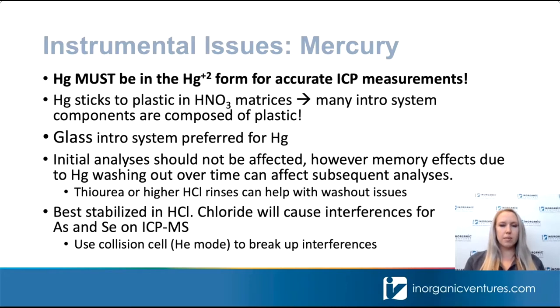The main thing to keep in mind when performing a mercury analysis on ICP is that mercury must be in the +2 ion form to achieve accurate results on ICP. Another thing to keep in mind is that mercury, when contained in nitric acid alone as the matrix, is going to stick to any plastic component, so it's going to absorb to those plastic surfaces, and many intro systems are composed of plastic. We do recommend using a glass intro system if possible for your mercury analysis.